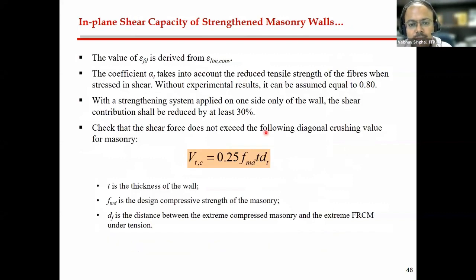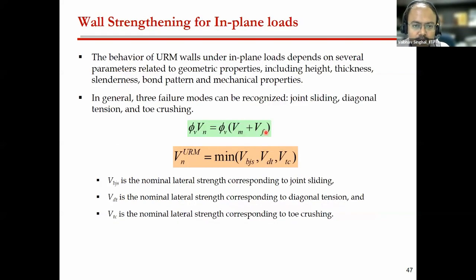The code also says that the total strength should not exceed the diagonal compression strength or diagonal crushing strength of your masonry. Otherwise, if you provide too much reinforcement or too much strengthening, it will not be very effective, because the masonry has a limited crushing strength and the masonry can crush inside, whereas your strengthening scheme will be intact. It is something like how we try to avoid over-reinforced design in concrete. Similarly here also, we don't want to provide an excessive amount of strengthening, because the masonry will fail early before the failure of your strengthening material. After finding out this V_f, your contribution of the strengthening material, in this case reinforced cementitious matrix, you add this to the strength of your masonry and you can get the total strength of your masonry wall or any component, any member with reinforcing or strengthening material.